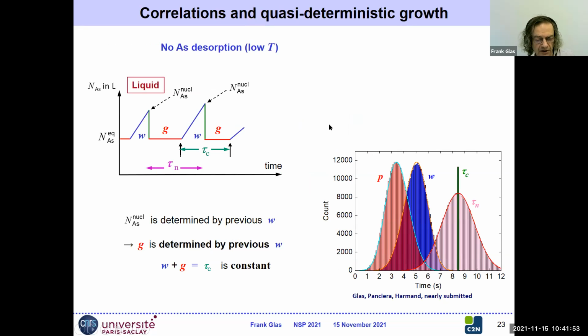So how can we understand this? Very simply. So we assume we have no desorption. During the waiting time before nucleation, the concentration in the liquid increases linearly. At some point, we have nucleation. And in the liquid, we'll have a certain quantity of arsenic atoms. And our simple picture is that we use part of this to form a monolayer. In other words, the fraction of monolayer we're going to form at nucleation, very fast, stage 1, depends on the waiting time before, because it depends on the number of arsenic atoms we will have accumulated in the liquid.